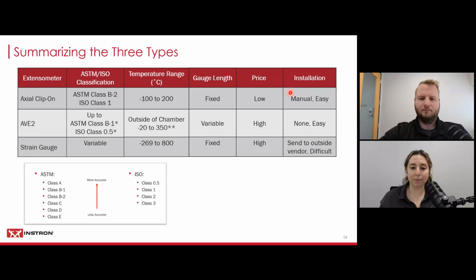They're very repeatable. The AVE2 is extremely easy as it's already set up. Really, you just need to make sure that you're marking your specimens with the proper gauge length. So we consider this easy. And then bonded strain gauges, we consider this difficult, as you might have to have the specimens sent to an outside vendor to be bonded, or have an operator doing this process for you and making sure that they're properly adhered to the specimen before test.